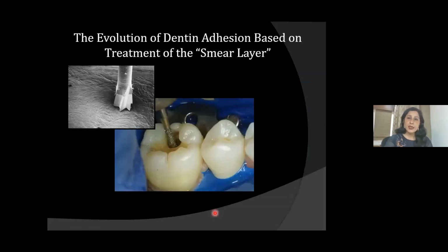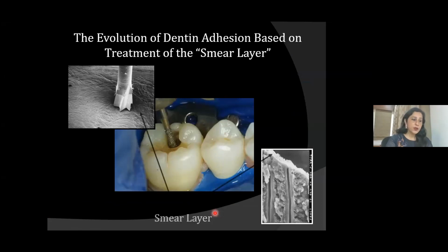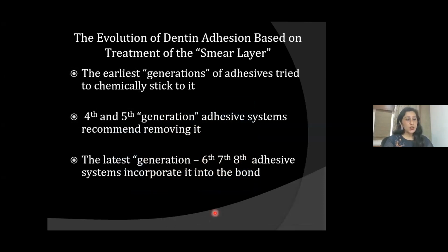The evolution of dental adhesion is based on the treatment of smear layer. Whenever the rotary instruments cut dentine, smear layer is created, which is 1 to 5 microns thick. It has hydroxyapatite crystals as well as partially denatured collagen, both of enamel and dentine. The evolution of dental adhesives is based on this smear layer. Now, the earliest generations of adhesives tried to chemically stick to it, whereas the 4th and 5th generation adhesive systems recommend removing it, and the latest generations, that is 6th, 7th, 8th, and now the 9th also, incorporate it into the bond.